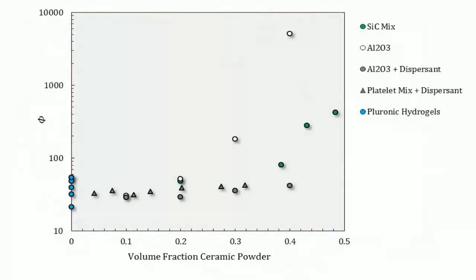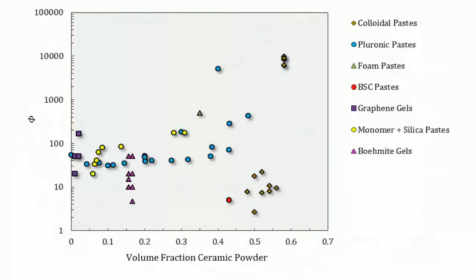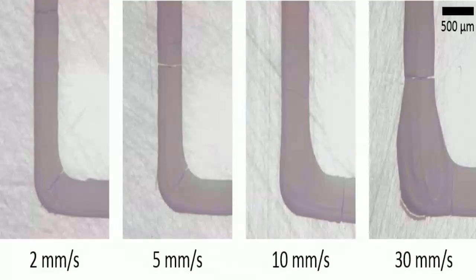Okay, so recapping the monolithic part: robocasting can make solid, reasonably strong parts. Density looks good, strength can be comparable to traditional methods, if done well. But it has clear limitations regarding resolution, handling complex geometry, and critically, these printing-induced defects that cause directional weakness and lower reliability. That sums it up pretty well.